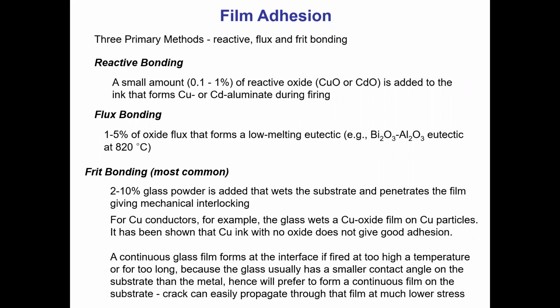And next, I'm going to talk about the bonding effect, bonding of the film to the substrate. There are three types of bonding mechanism that is used, so-called reactive, flux bonding, and frit bonding. In reactive bonding, the idea is to add a small percentage of reactive oxide like copper oxide or cadmium oxide that will react during firing with the substrate like alumina and form copper aluminate spinel or cadmium aluminate spinel that keeps bonding. It's basically going to pin your film at dispersed location and improve the bonding of the film to the substrate.